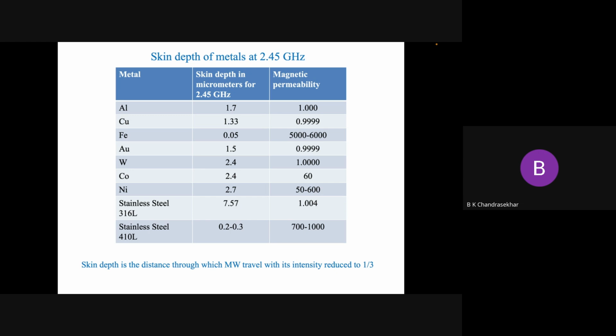Now here I have mentioned the skin depth of typical conventional metallic materials, and most of them are in the order of 1 to 2 microns. Okay, and some of them are much lower, like stainless steel, last row, stainless steel 410L, which is only 0.2 to 0.3. That means the microwave is fully absorbed at a very thin layer within that particular material.